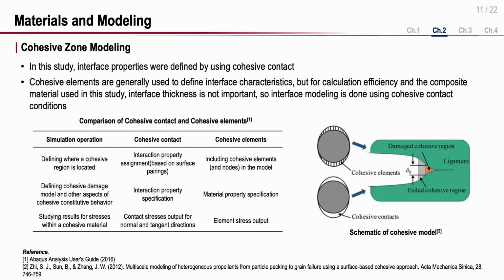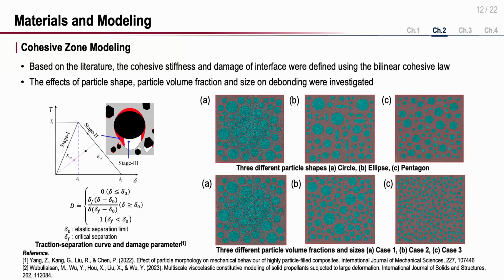And this slide is about cohesive zone modeling for defining interface characteristics. There are 2 ways to model an interface by using CZM. One is cohesive contact, and the other is cohesive elements. And in our study, interface properties were defined by using cohesive contact. And based on the literature, the cohesive stiffness and damage of the interface were defined by using this bilinear cohesive law. And we performed case studies regarding the effects of particle shape, particle volume fraction, and size on debonding.